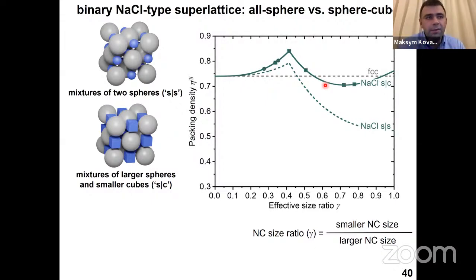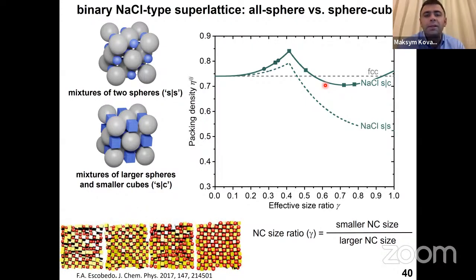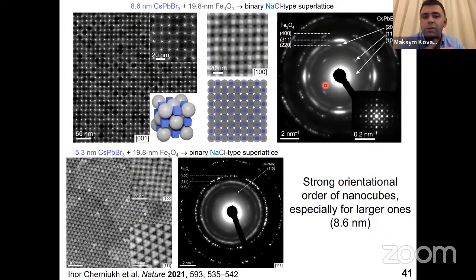And we tested this, and there were theoretical predictions that this is the case, even years before our work. And indeed, we observe a superlattice where the perovskite cube is surrounded by these spheres of iron oxide or another compound, in this case it's iron oxide, but it also can be some dielectric material.